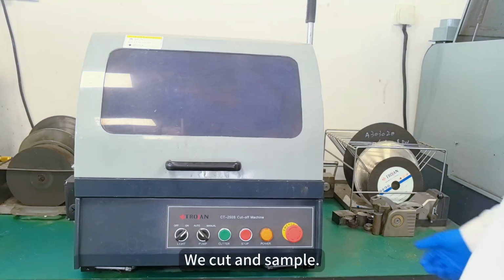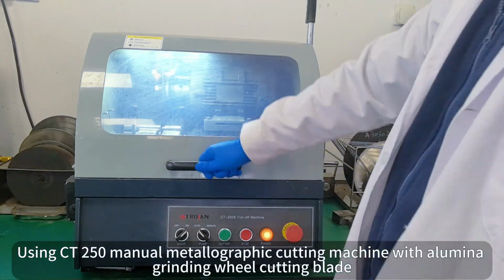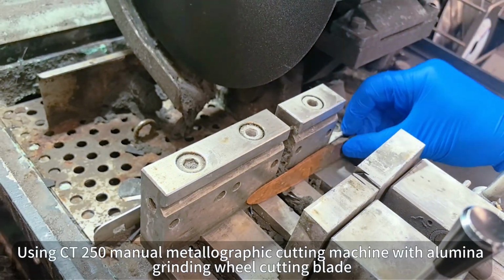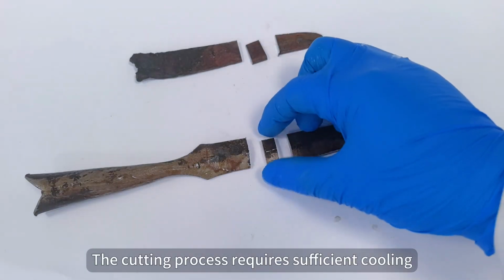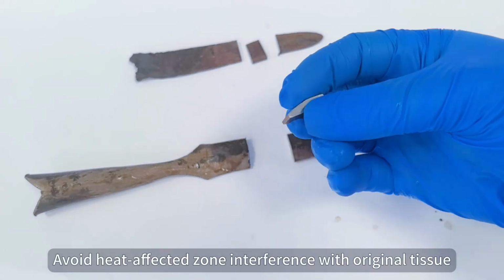Cutting. We cut and sample using a CT250 manual metallographic cutting machine with an alumina grinding wheel cutting blade. Representative samples were cut from the middle of the knife embryo. The cutting process requires sufficient cooling to avoid heat-affected zone interference with the original tissue.